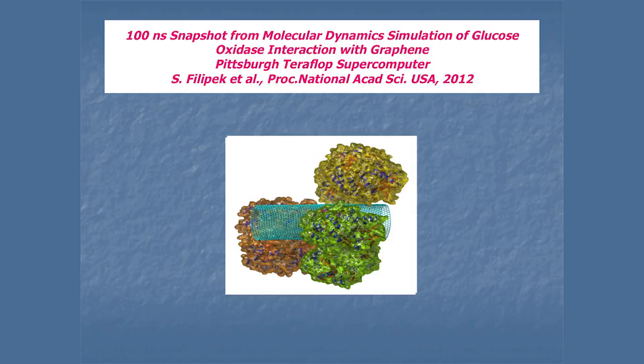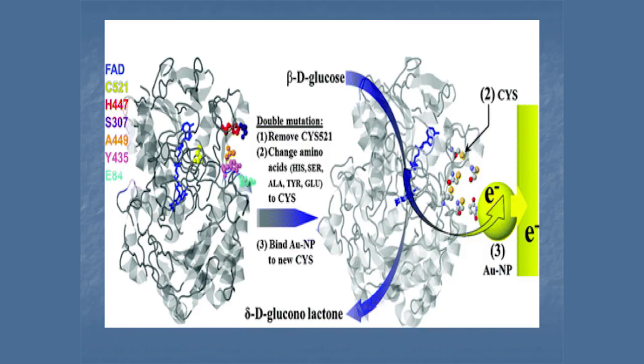We're trying to make the interface between single layer graphene and the protein as efficient for optimal transfer of electrons. Now, there's a crosstalk between the enzyme, the probe, and the graphene surface. Electrons get quite lost, although the electrons can travel up to 30, 40 angstroms quite easily. So the current that you observe is directly proportional. That is where the FET sensor becomes very sensitive.